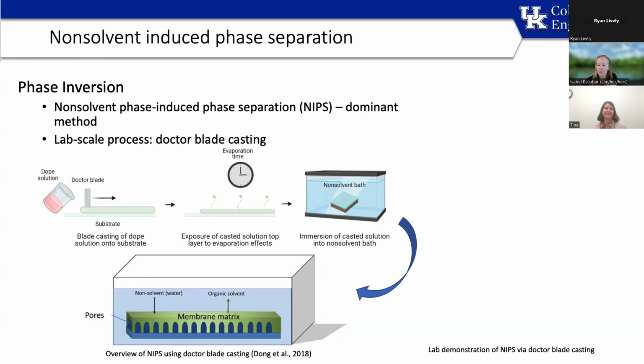So in order to make membranes using NIPS, we take the polymer, we dissolve it in the solvent to make the dope solution. That's pretty standard. We then spread that dope solution on a substrate. We move a Dr. blade over it. It evaporates over time. Then we put it in the non-solvent bath, and then we have the membrane.